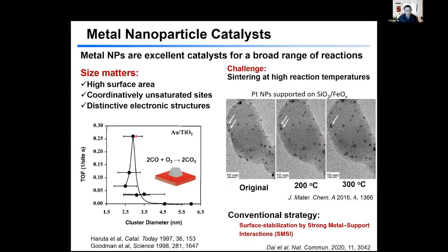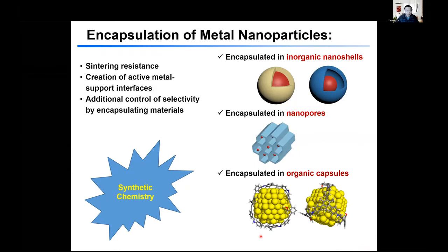You can imagine if you have perfect size, when they merge, their size doubles, and then your catalytic activity disappears, right? And so that's a challenge. In the catalysis community, people already realize that, and they start to use so-called strong metal-support interactions to stabilize the nanoparticles on the surface. The problem here is that this strong metal-support interaction is very specific to the materials combination. It's not general. So in the colloidal chemistry community, we actually try to address that.